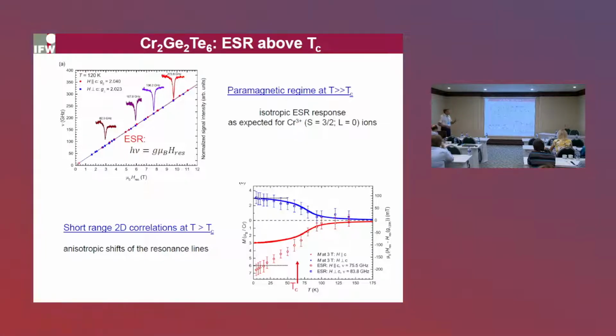This is a signature of the development of low energy, low frequency spin-spin correlations, which generate quasi-static local fields on the ESR time scale. But importantly, these shifts start to develop at temperatures twice as large as the ordering temperature. This is very unusual for a conventional three-dimensional magnet, where as soon as the correlations start to develop in all three dimensions, the magnetic order sets in. And that was the first indication that even in the bulk crystal, we see short-range two-dimensional correlations at temperatures far above the ordering temperature.